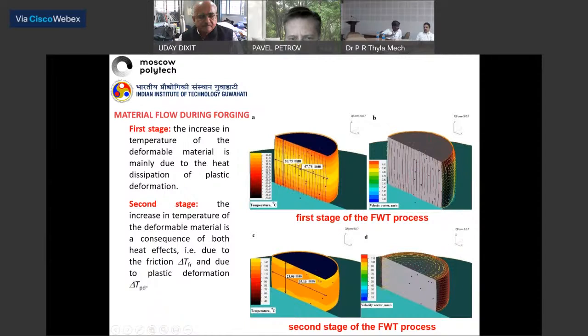Conditionally, on the first stage, the common axisymmetrical upsetting is performed. The value of upsetting is not more than 30% of the initial height. And just after that, the rotational moment is applied to the workpiece, and the workpiece continues to deform along the longitudinal axis. Within this second conditional stroke, the rotational moment affects the workpiece, and due to shear stress, shear deformation, the diameter of the workpiece increases while the height of the workpiece decreases.